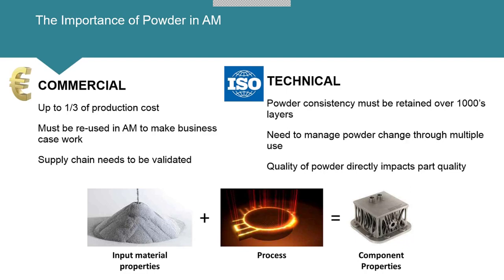So you've got to make sure that powder is consistent for every single layer you spread. Because I mentioned commercially you have to be able to reuse the powder, you need to therefore manage powder change through multiple use. There's a classic issue with titanium, for example, where the more times you use it, the more oxygen you pick up. Eventually you will pick up too much oxygen, you'll be out of spec. So you've got to be able to understand how to manage the reuse of powder in the AM process.